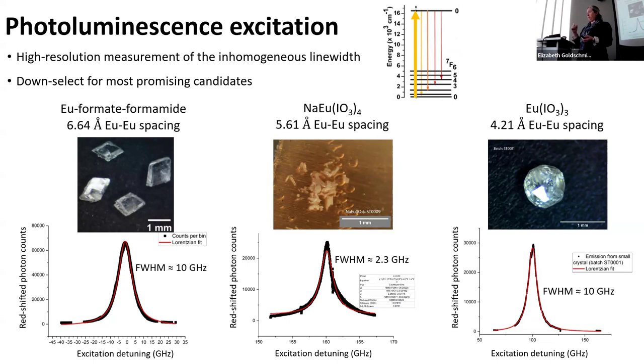And so we fed a bunch of things into a system and just started growing things. We also tried a lot of other things that for one reason or another didn't work. We also wanted growth methods that we thought would be relatively low defect. So this is all grown in solution, either near room temperature or at elevated temperatures in a hydrothermal scheme. Yeah, so we are working with a proper real material science group as well. We're not just a bunch of physicists wandering around in the dark, which helps.